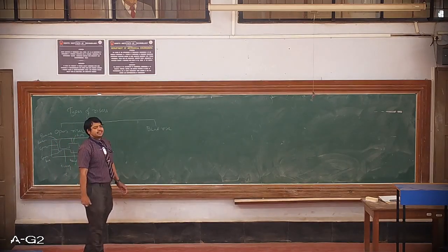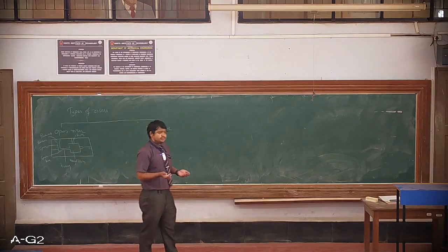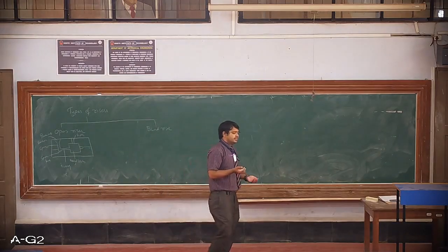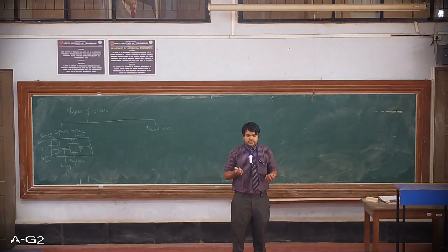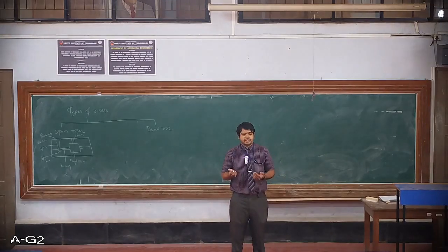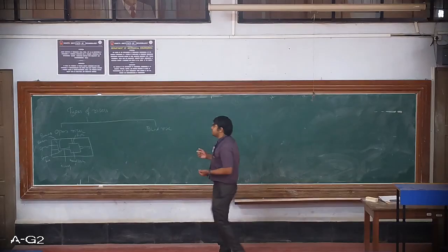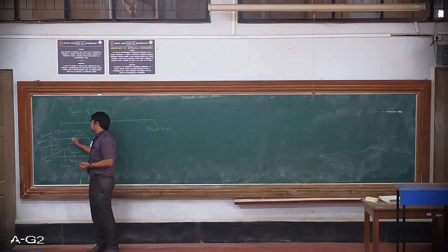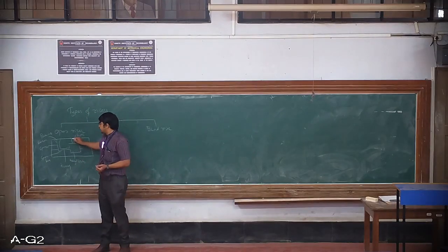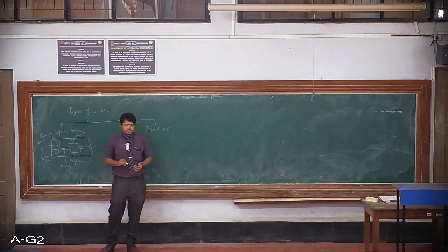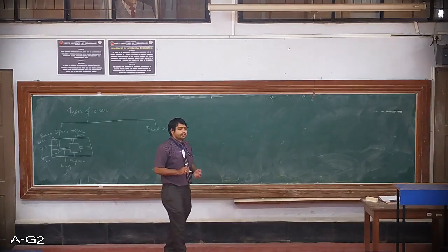So in most of the cases where the gas generated will be more, in the case of heavy castings, in the case of castings which generally give out a large amount of gases, we generally go for the open type of riser. The drawback of this is that the layer at the top is going to solidify, and sometimes because of this there will be a pressure drop inside, and this will give rise to reduced feeding force. Because of that the shrinkage effect will occur.